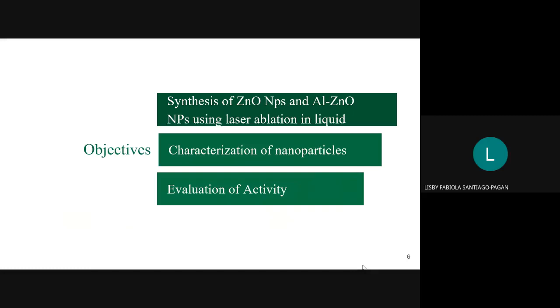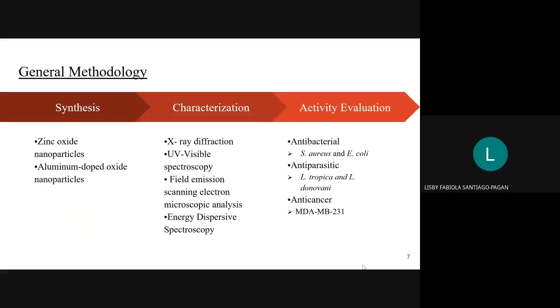The objectives of this study were the synthesis of zinc oxide nanoparticles as well as aluminum doped zinc oxide nanoparticles using the laser ablation in liquid technique, the characterization of the nanoparticles, and the evaluation of activity. Initially, the synthesis and doping with aluminum were carried out using the liquid ablation technique, as I previously mentioned. Then the resulting nanoparticles were characterized using X-ray diffraction, UV-vis spectroscopy, field emission scanning electron microscopy, and energy dispersive spectrum analysis. Finally, the activity evaluation of the nanoparticles was done to review their potential as antibacterial, antiparasitic, and anticancer.